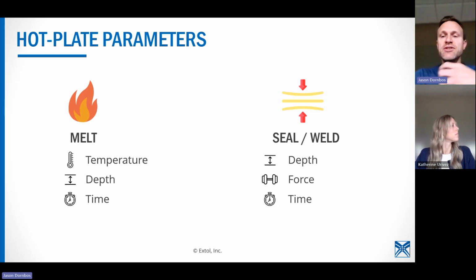Obviously, the hotter your heated tool, the less amount of time it takes to get that heat into the plastic. For polypropylene, what are the temperatures? Polypropylene is one of the most flexible materials as far as what temperature you can use. You can weld it at what we call a lower temp or a higher temp. Pretty commonly we like to use a hotter temp just so the process is faster, but some customers prefer the lower temp. They think that it maybe will provide stronger results long term. A pretty average lower temperature would be 500 degrees Fahrenheit, and the upper temperature maybe 850 degrees Fahrenheit for polypropylene.